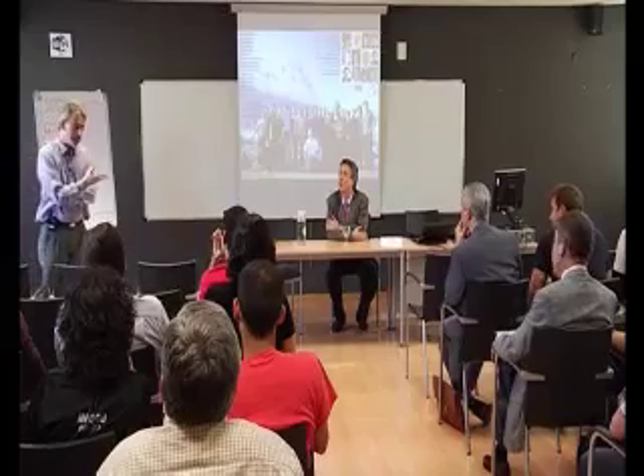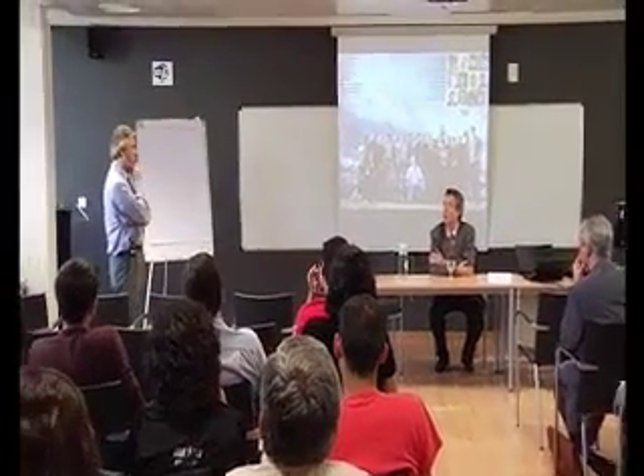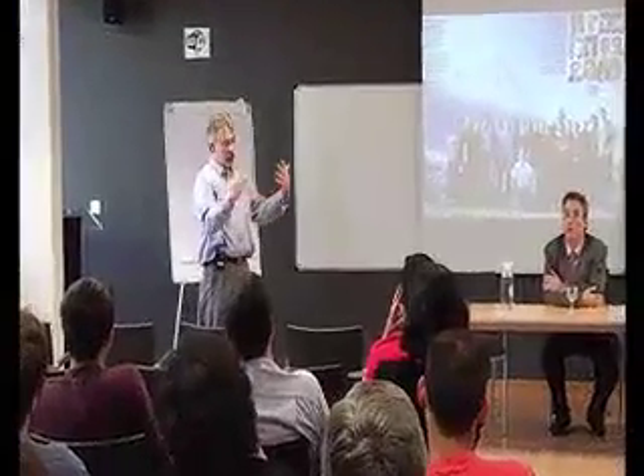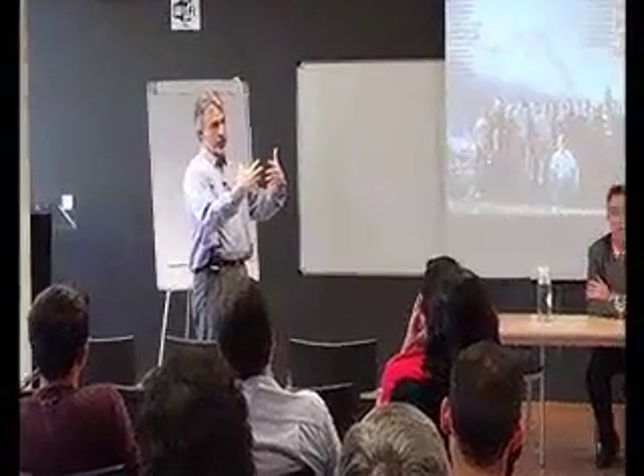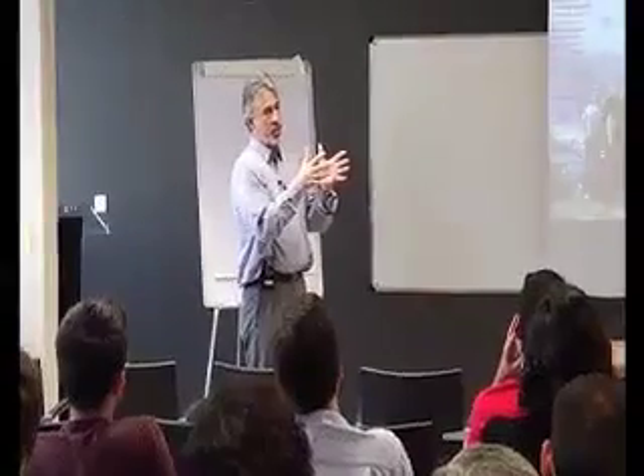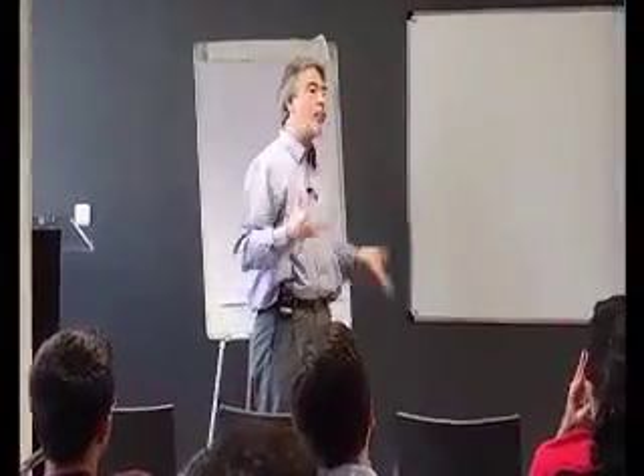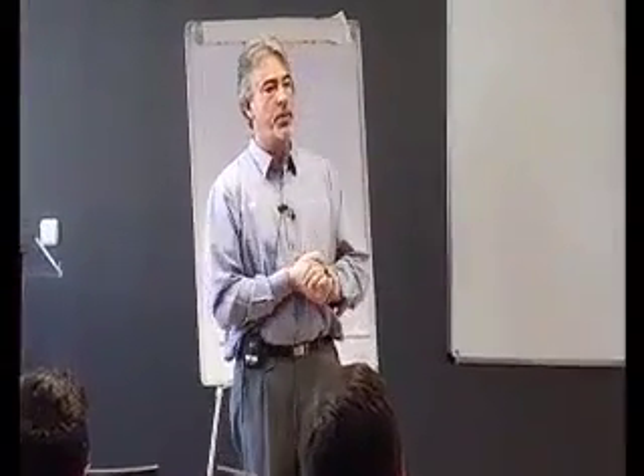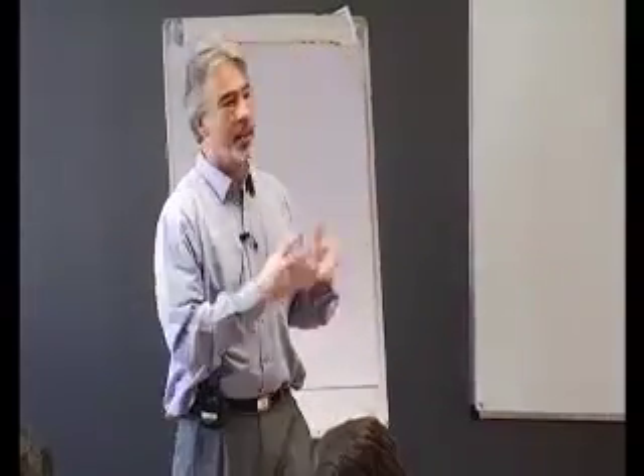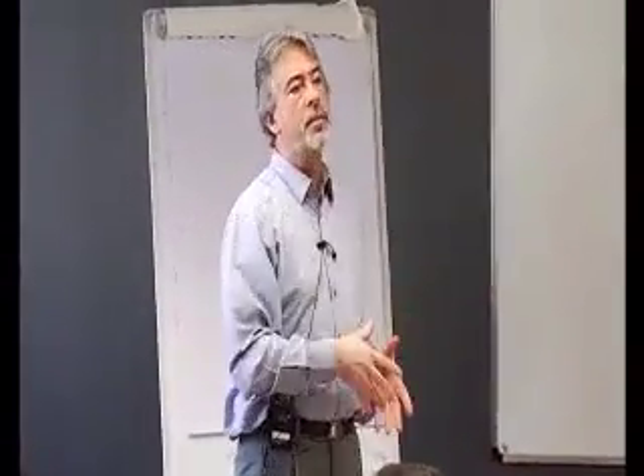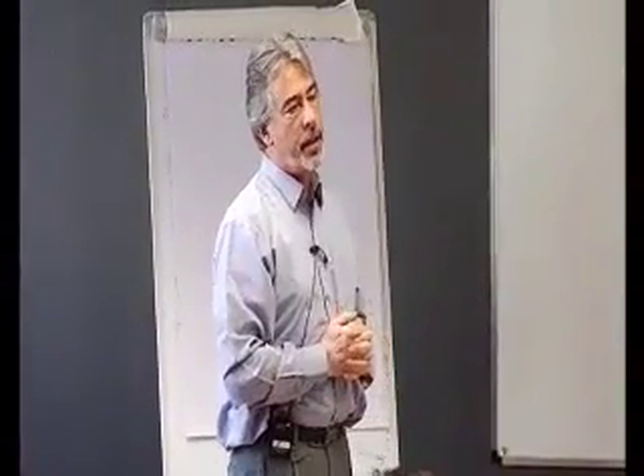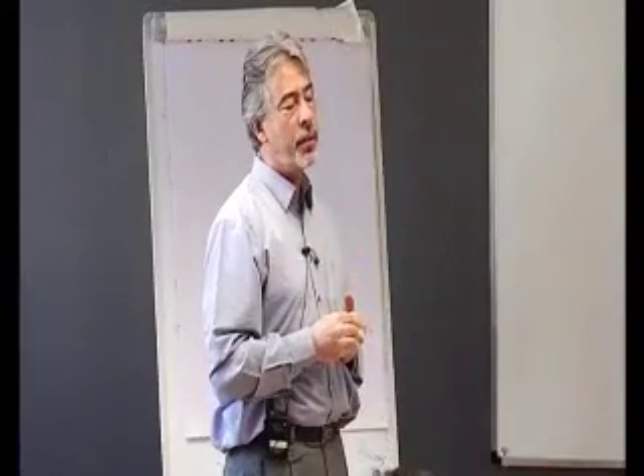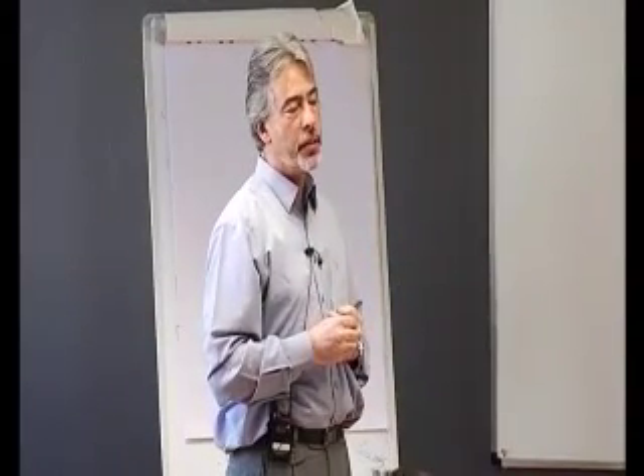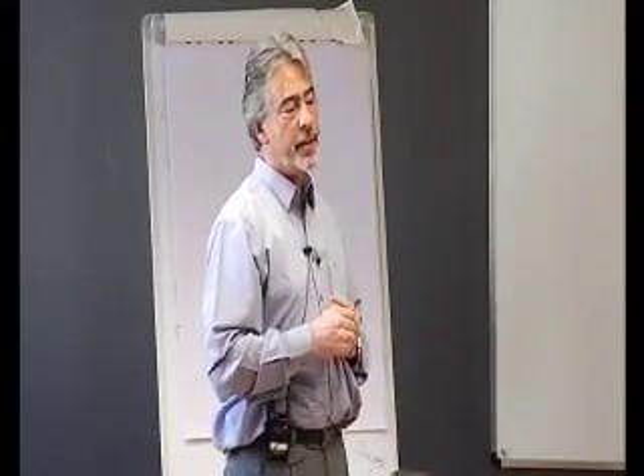Nosotros no hemos intentado, pero en el grupo de Weimer en Colorado, ellos utilizan un reactor que tiene porous walls and they inject argon under pressure to prevent particle deposition. And they have some kind of mixed results. Sometimes it works, sometimes not. We haven't tried. We just took a quartz vertical reactor. And that may be a way to go to avoid deposition of particles.